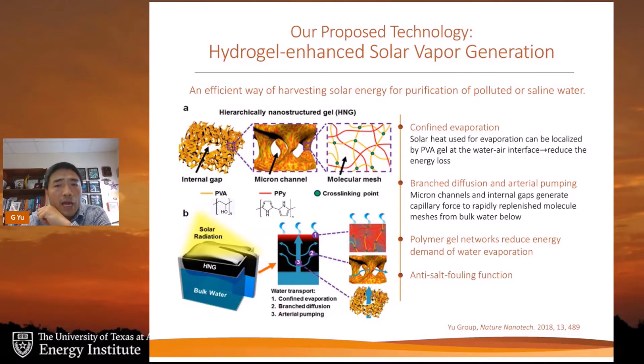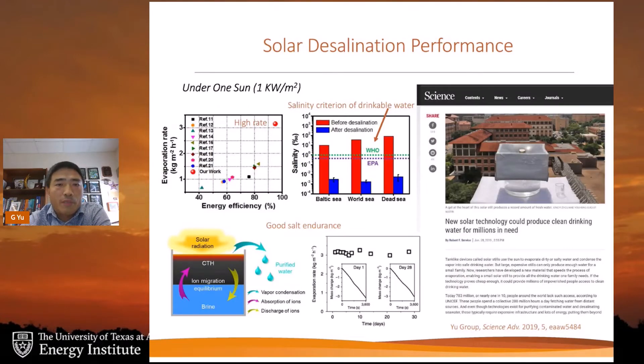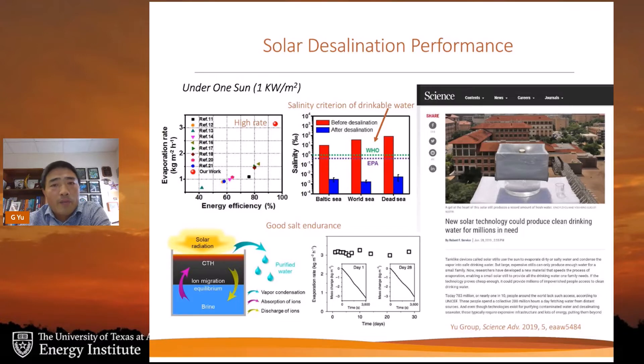The hydrogel has hierarchically structured channels that concentrate sunlight while capillary forces enable very efficient water transport, so once water evaporates at the interface it can be efficiently transported from bulk water. This slide shows the differences between our hydrogel technology versus others: our evaporation rate is almost double the state of the art under one sun, and the evaporation efficiency produces water well below EPA-required salinity levels. The hydrogel also shows efficient anti-fouling, enabling long-term water desalination demonstrated from several weeks to about a month.